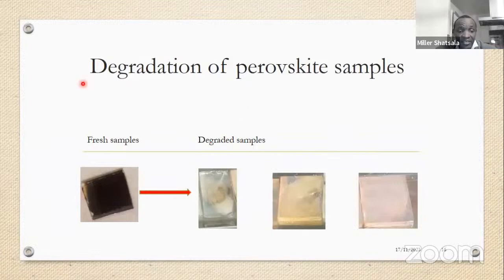So we had our samples from our lab, which we came with. Unfortunately, this material is very unstable, and because of bureaucracy, visa issues and so on, there were delays. So we took some time before we tested this sample. When we arrived with it, it had degraded a bit. You see the color has changed from the dark color and is turning back into yellowish, which signals some degradation. So we still went ahead and did some preliminary measurements to see how the film behaves.